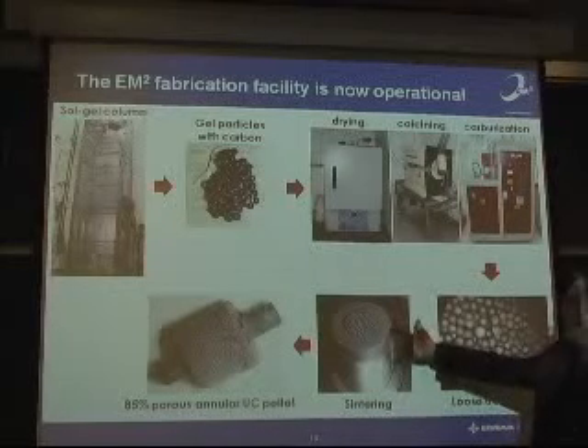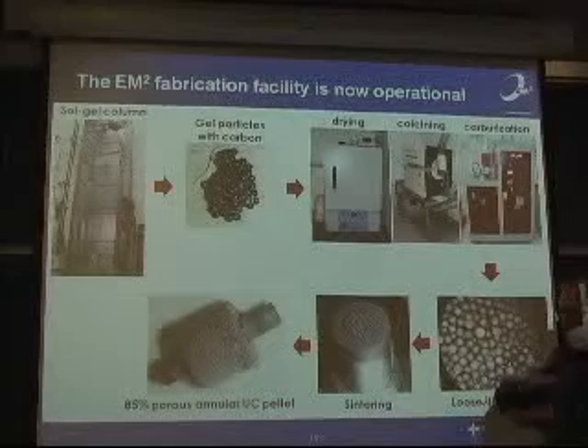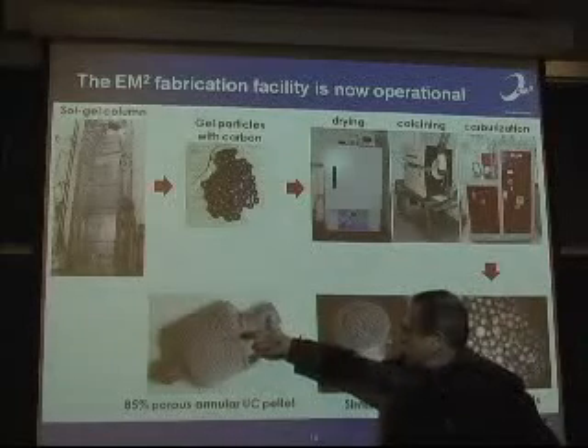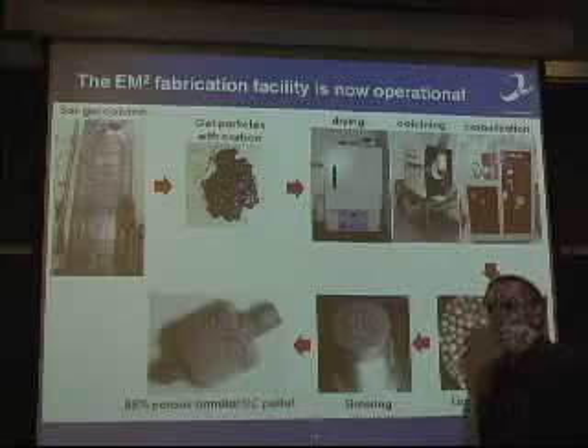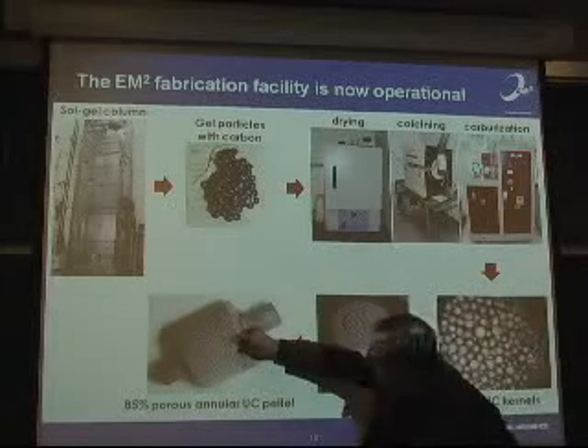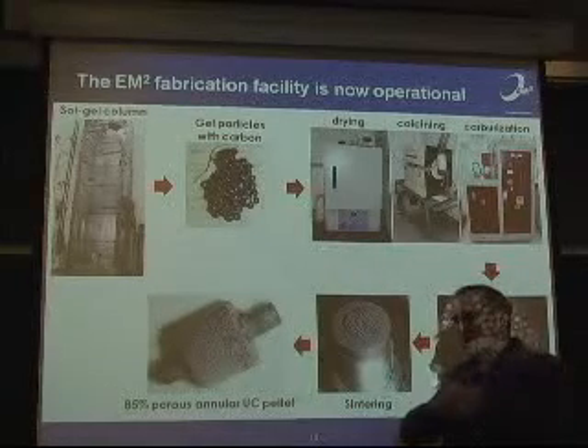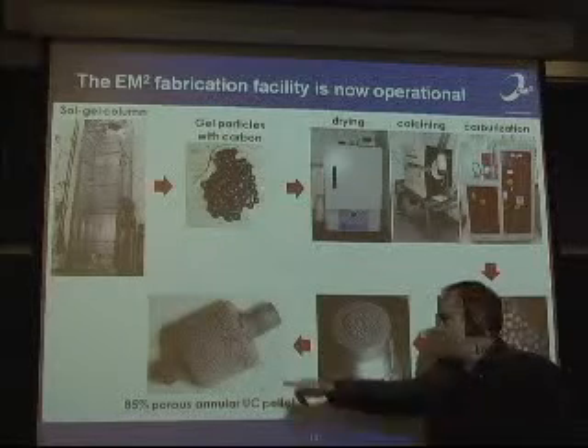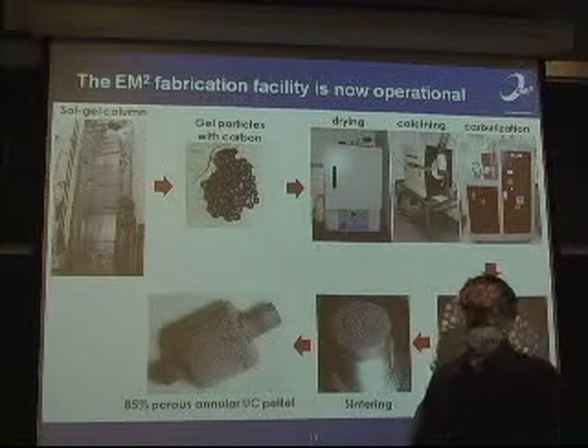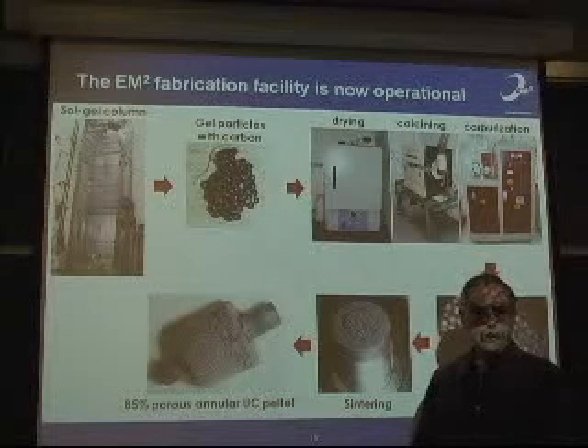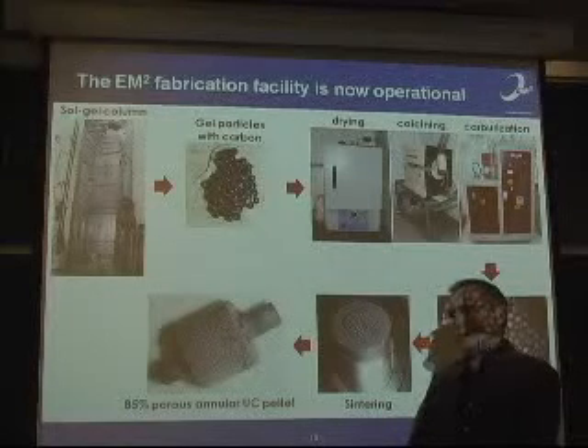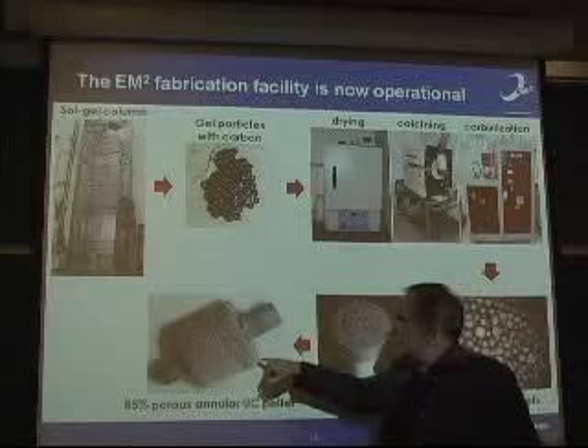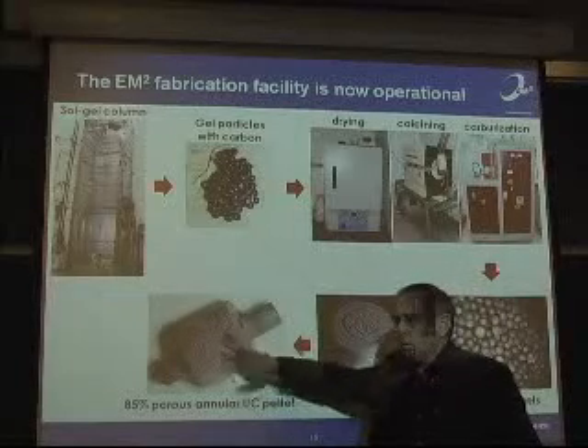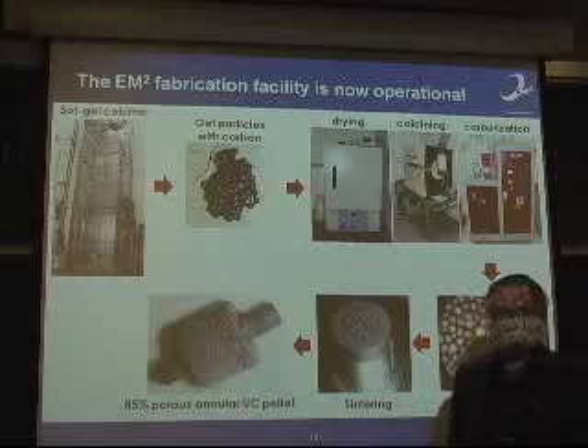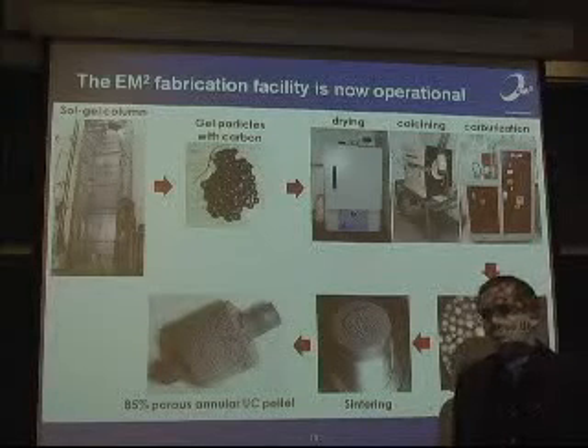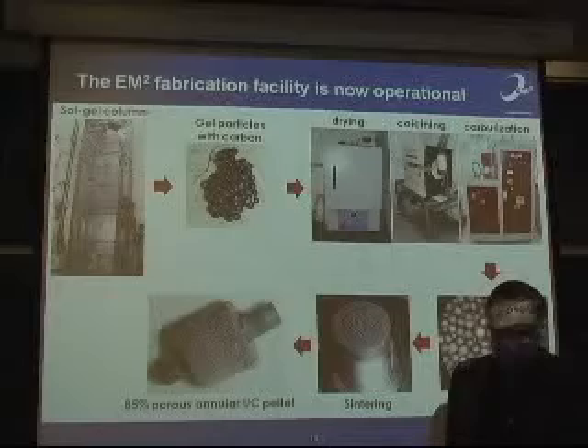This just shows a sintering experiment in which we do it by pressure. We actually want to make annular particles, and we have to guarantee that all these particles have really good contact thermally, so we have good thermal conductivity. So we're investing in spark discharge sintering processes to be able to do this, so that through a large electronic spark, we weld all these particles together and get good thermal contact. So this is a very innovative way of sintering material that we're working on.